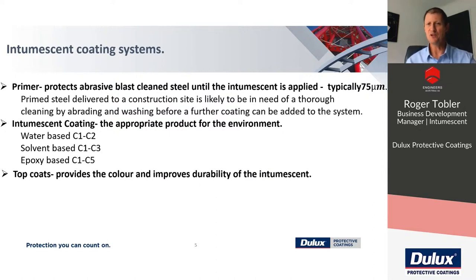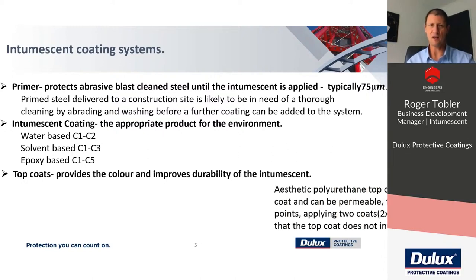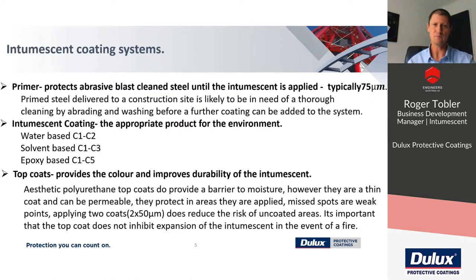Top coats are going to add durability to your intumescent, and the other function of the top coats is to add a gloss level and to give you the required color. The most durable top coats that can be used with intumescents are polyurethane top coats. They're two-component products. They give you a good barrier to moisture. However, we must remember they're thin. They're typically 50 to 75 microns.